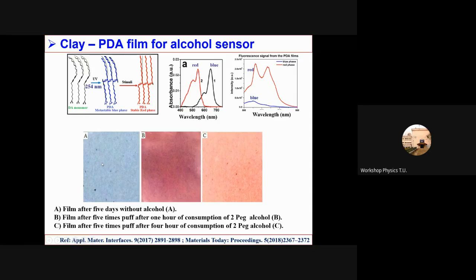And what we have seen, in the first picture, we prepared the film, then using UV we converted the film into blue phase. And this is the image using a normal optical camera. Then we exposed this film to alcohol. You see, the film after 5 puffs, after 1 hour of consumption of 2 pegs of alcohol. You can see picture B is red. That means this polymer changes into the red form.